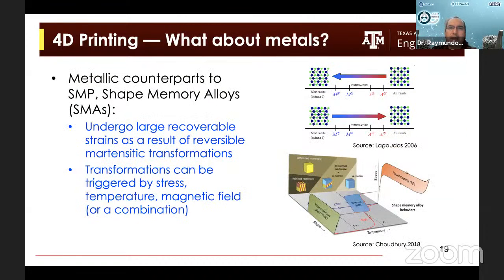Okay, now what about metals? So I mentioned shape memory polymers. In metals, we have something called shape memory alloys. And these are metallic alloys that undergo large recoverable strains as a result of reversible martensitic transformations. Martensitic transformations are transformations that are not diffusive. In this case, what happens is you have a crystal structure, you have a martensite, and then when you increase the temperature, you go to austenite.